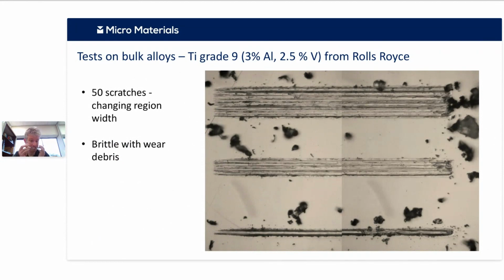So these are just an example where we have titanium grade 9 essentially, and here we're just doing these randomized scratch tests. This is 50 scratches in these 3 tests, but all that's happening is we're changing the region width. So in the bottom one, all the scratches are in the same position. Above it, they're slightly closer together, and then above it still they're a bit wider apart. And you can straight away see all of this brittle damage around the edges where you're getting these brittle machining